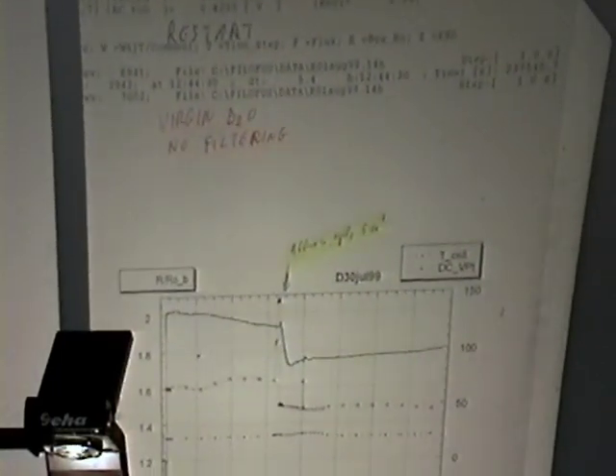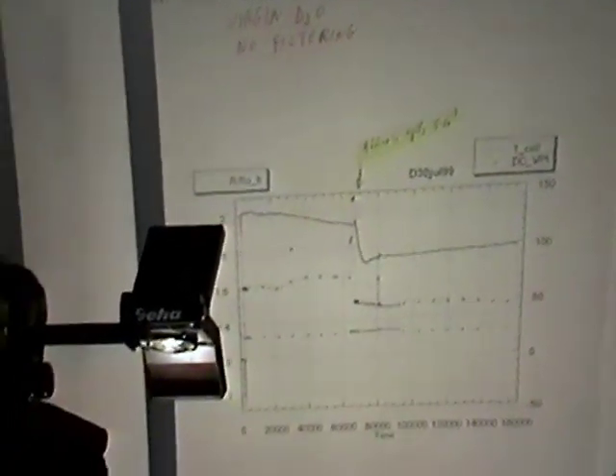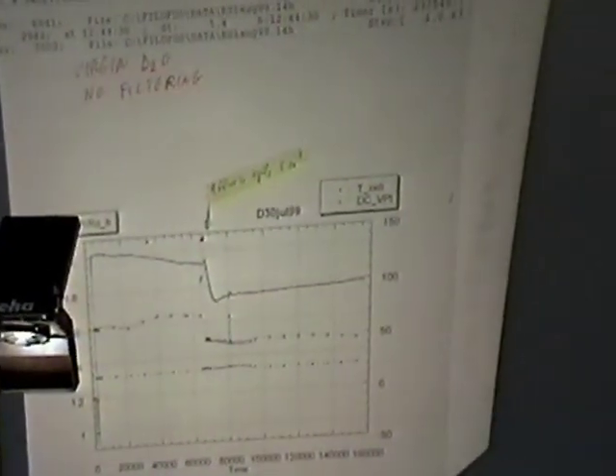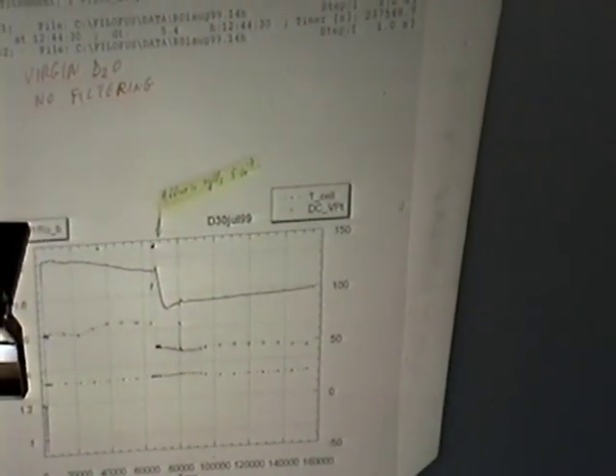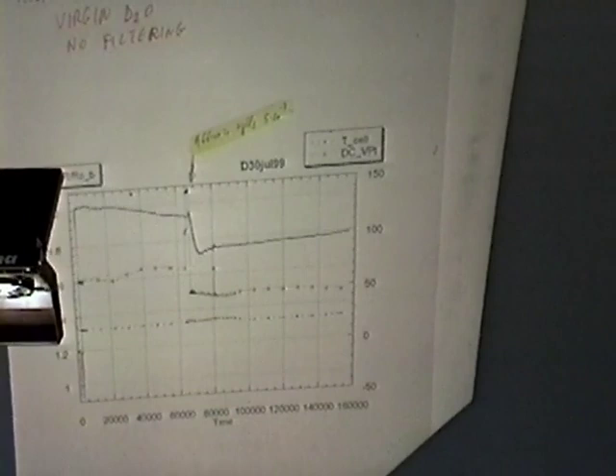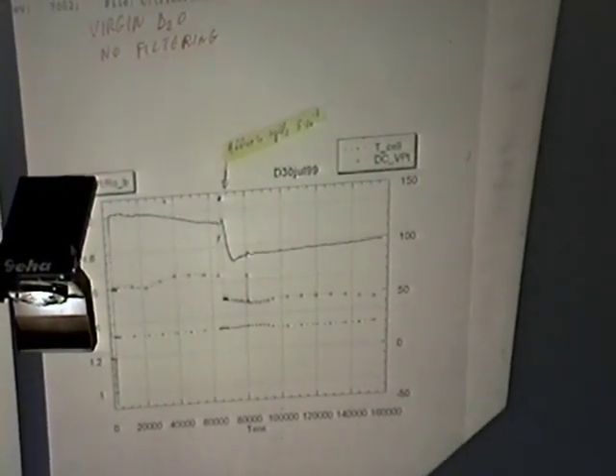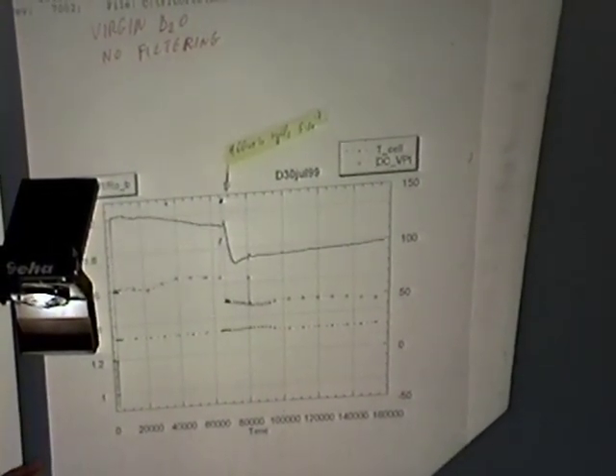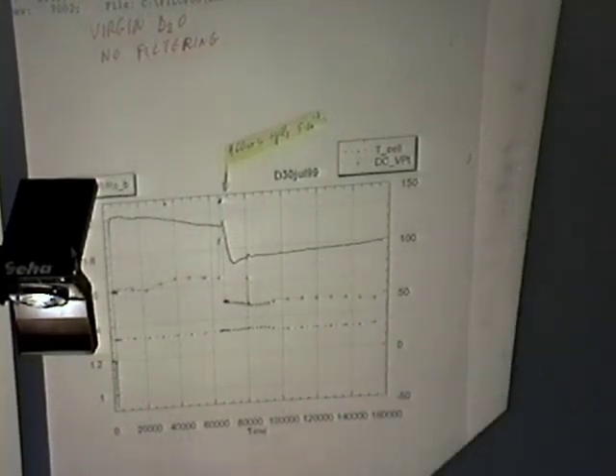So, an experiment with pure virgin deuterium oxide without filtering, the loading reached about resistance ratio 1.9. We added some mercury, the loading improved, but after some time it was lost again, to resistance ratio 1.8. Not enough for our purpose.